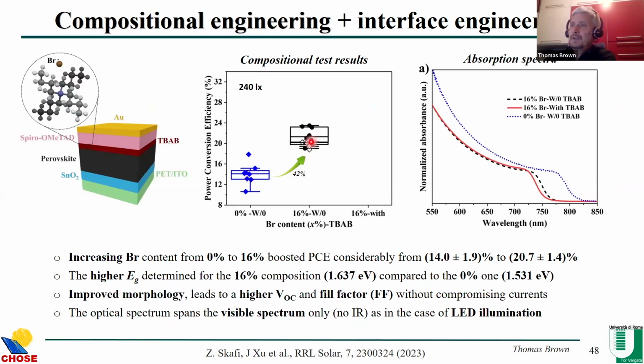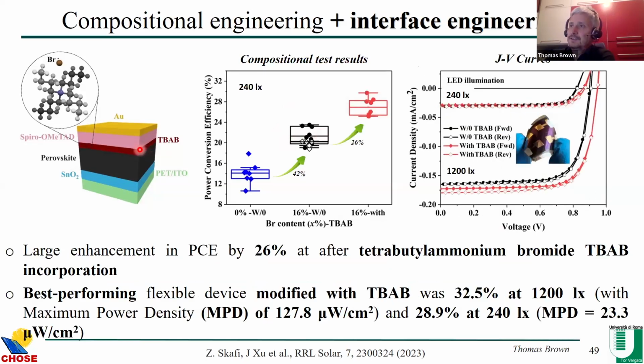So if we use zero bromide, so the standard perovskite, the efficiency was around 13–14%. When we increased the bromide content to 16%, we achieved an efficiency increase of 42%, up to around between 20 and 24%. When we applied the TBAB, which is interface engineering, the efficiency increased by a further 26%. And the efficiency on these plastic devices was around 32% at 1,200 lux, around 29% at 240 lux. So one for like supermarket environments and the other for homes.